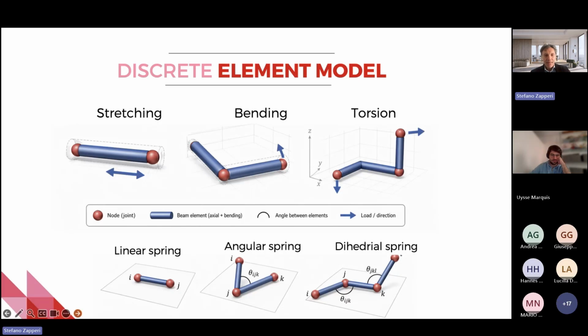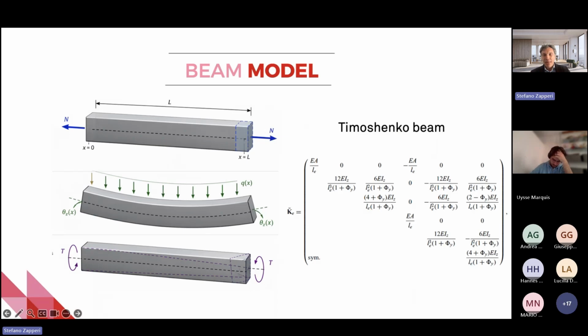But then we also use a different class of models that is more mechanical engineering inspired, which is the beam model. Now every element is not a set of point nodes connected by all these springs, but a full 3D elastic body, quasi one-dimensional, which is a Timoshenko beam. A Timoshenko beam can undergo stretching or compression, bending, and torsion. All this is represented by a stiffness matrix. In this case, it's a 2D stiffness matrix, just 6 degrees of freedom. In reality, when we do 3D beam models, we have a much larger one, but it didn't fit into the slide, so I just showed it in 2D.